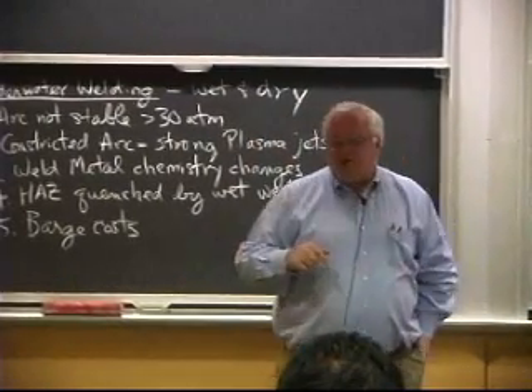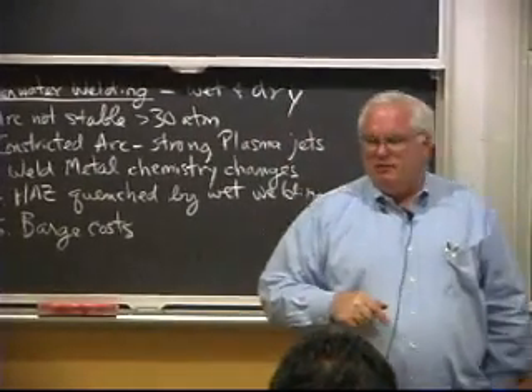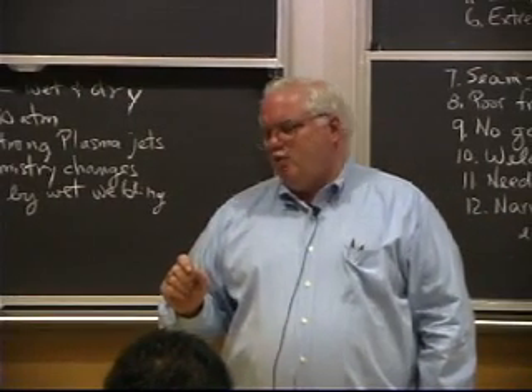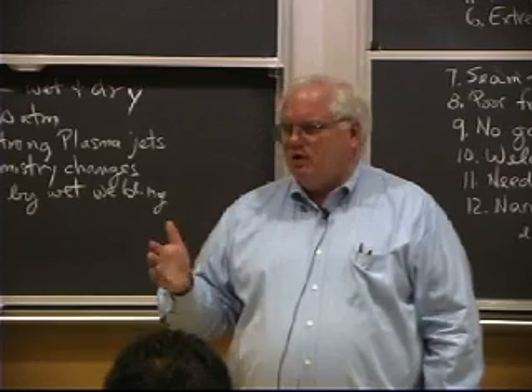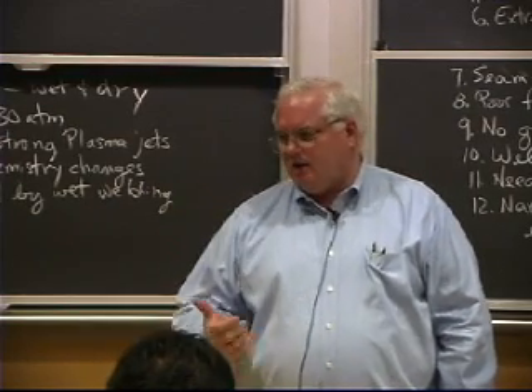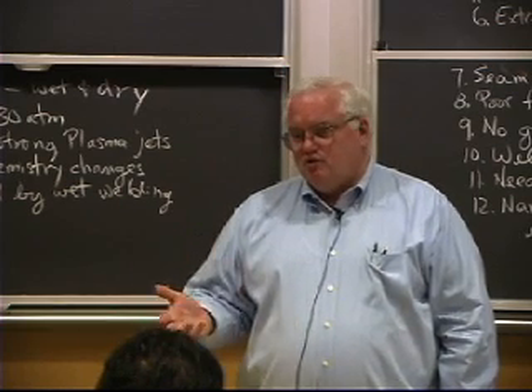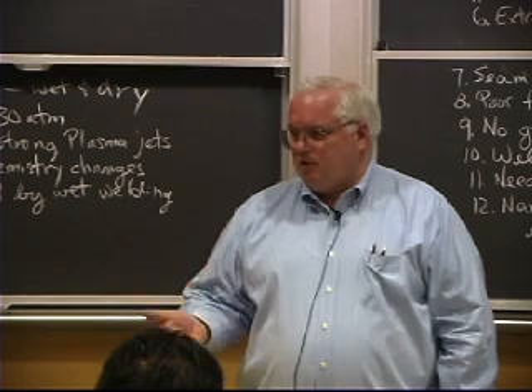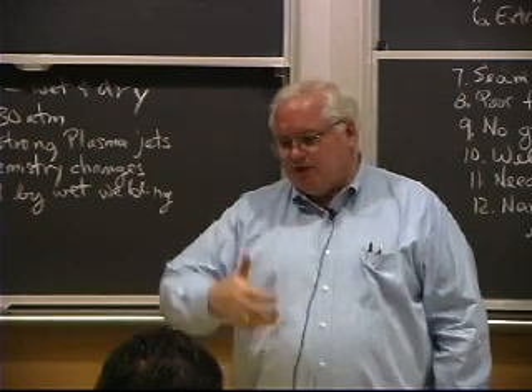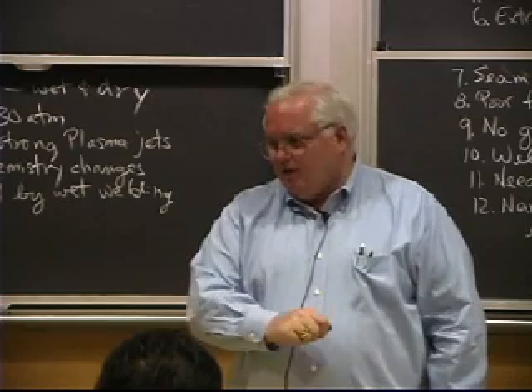So you get a constricted arc, you get stronger plasma jets. The stronger plasma jets cause greater gouging of the weld pool. Typically, you can weld up to 200, 250 amps before the plasma jets get so strong they start digging metal out of that weld pool. But in wet welding, depending on the depth you're going to, you may only be able to get to 125, 150 amps before that constricted arc gives you stronger plasma jets to start essentially digging holes in the metal rather than just kind of melting the metal and leaving a nice simple little bead.